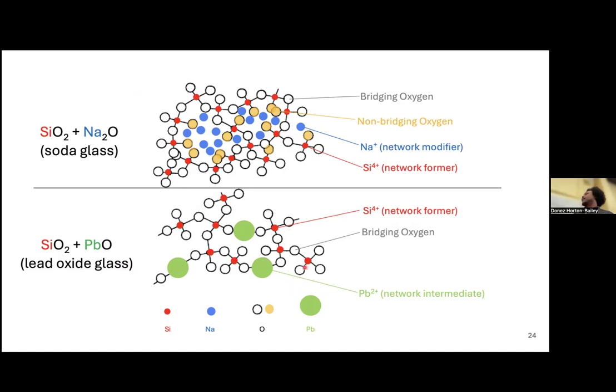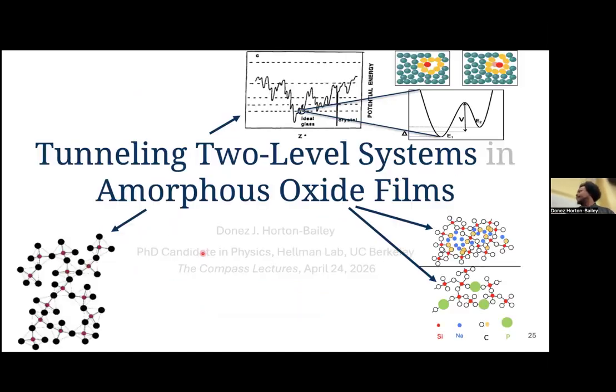This is a picture showing what's going on. In the top one, I'm using sodium oxide, or soda glass, as the modifier, and so we have these floating Na plus ions, and then we have these yellow oxygens that only have 1 bond instead of 2. In the bottom case, we have lead oxide being added, and lead actually substitutes. It takes the place of the silicon, and so it is able to incorporate itself into the glass. All right, and so this explains the oxide films part of the title.